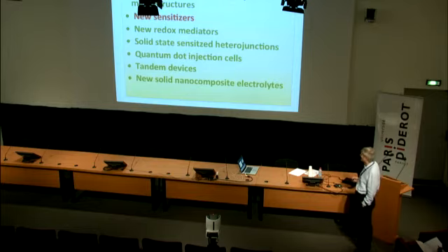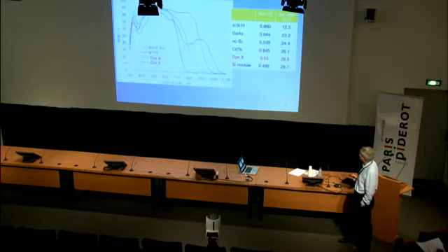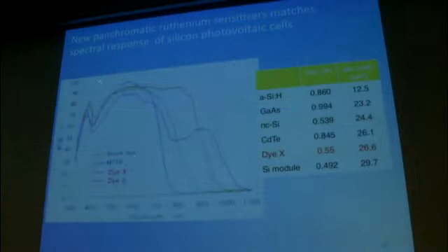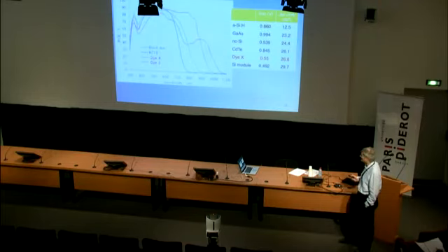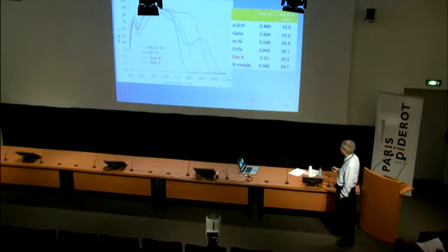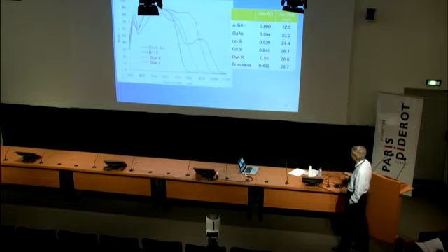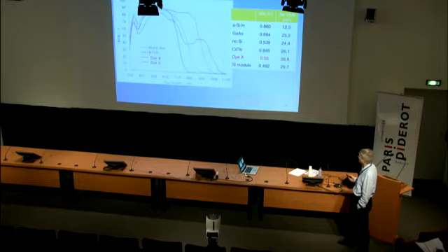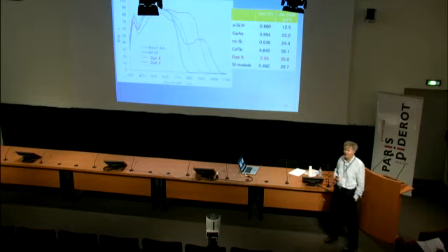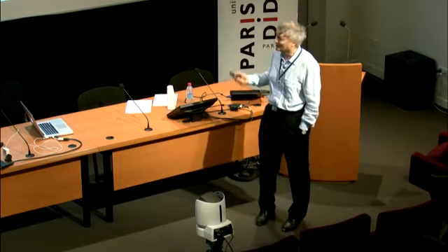So, the various structures. The latest in the sensitizer is this ruthenium complex. See, this was our standard. I showed you the structure. The green curve is for the black dye. It's a very similar structure. This was also a Lausanne invention. Then come the Japanese colleagues from the University of Tokyo, and they have a better response. They go up to 1,000 nanometers. This is amazing. It's one sensitizer molecule that gets a very similar photon collection and conversion to a silicon photovoltaic cell. It's a molecular silicon photovoltaic cell.